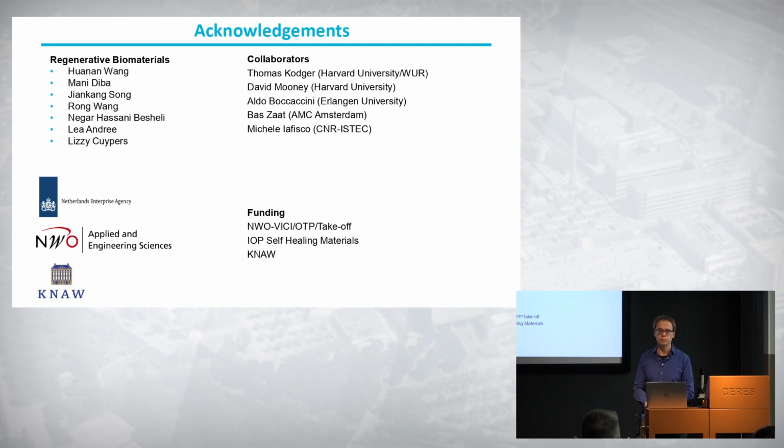Do I get correctly that that's just hydroxyapatite with zinc and there's no more vancomycin present in that? No, so we have two components. One is the inorganic nanoparticle, that's zinc-doped HA. So the zinc is really inside the particle, inside the lattice, which we would like to combine with gelatin, which is then loaded with vancomycin. So the gelatin was loaded with the drug still? Yeah, exactly. And we show that both of them are internalized and then effectively killing the bacteria.